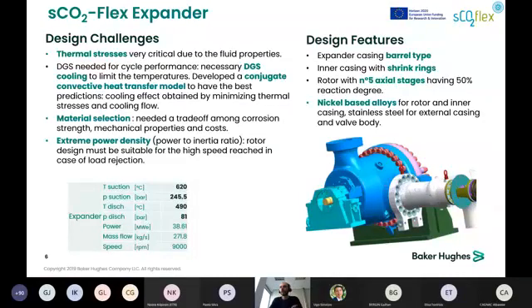But we have to consider that in this situation the supercritical CO2 is characterized by a high heat transfer coefficient, so the thermal stresses can be critical and must be carefully considered. For this reason, and considering a possible full load rejection that can happen during the entire turbine lifetime, the design choice has been to use nickel-based alloys for the rotor and inner casing, instead of standard martensitic steel, which has been kept for the external casing and valve body.